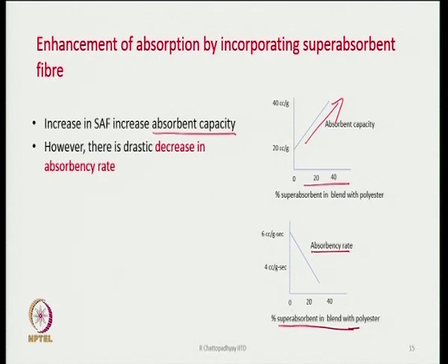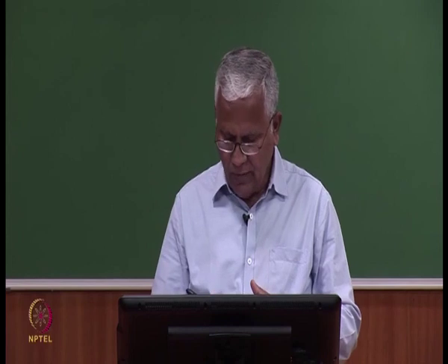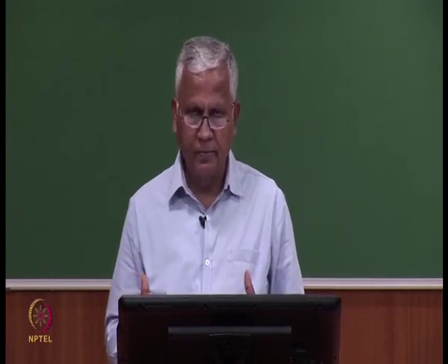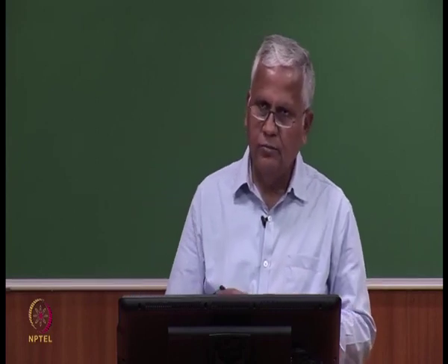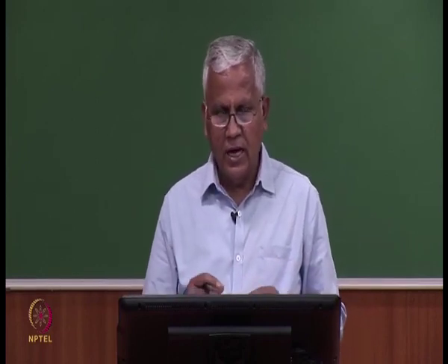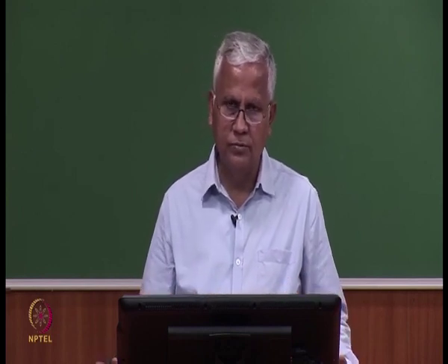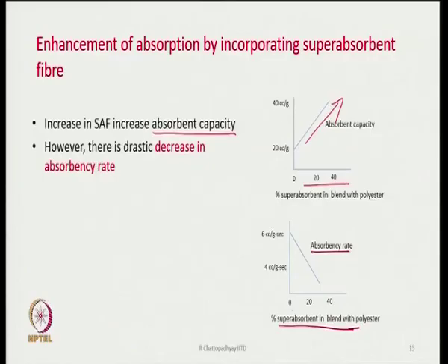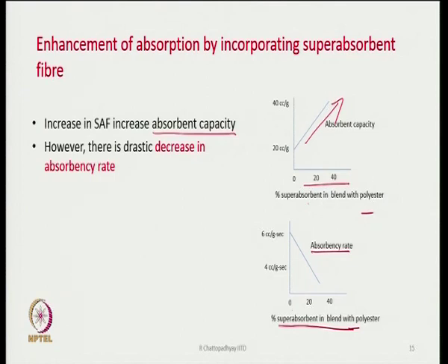The super absorbent polymer, once it absorbs some water, transforms itself. It becomes a viscous liquid. The polymer itself completely disintegrates, and it will now behave like a viscous liquid. And what happens is that it can block many pores as a result. Therefore, if I use too much of this super absorbent fiber, the overall capacity may go down, because it will block many pores and will not allow the other fibers to absorb. That is the danger with this.